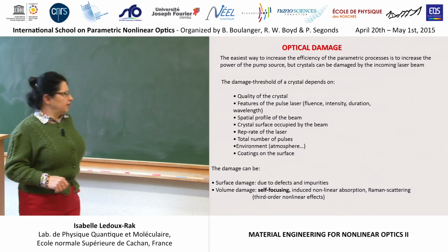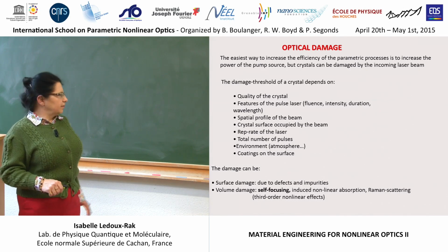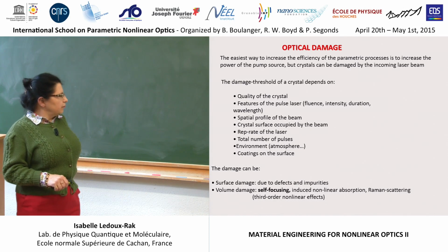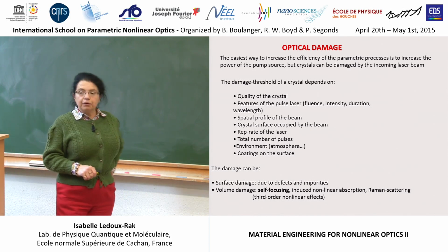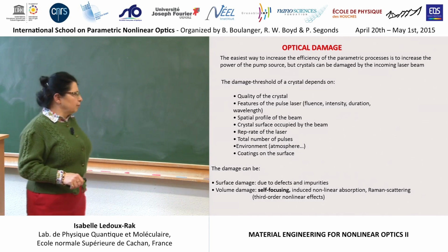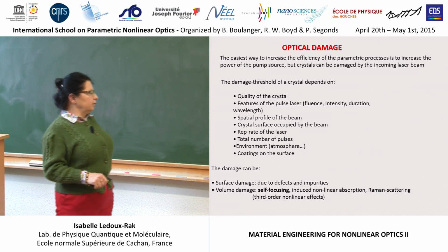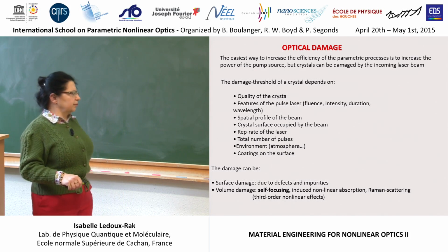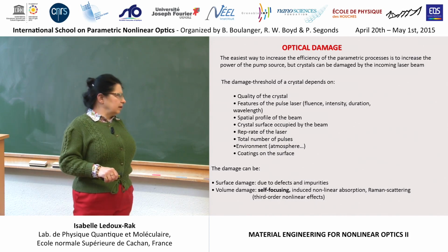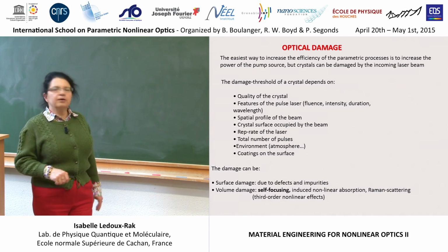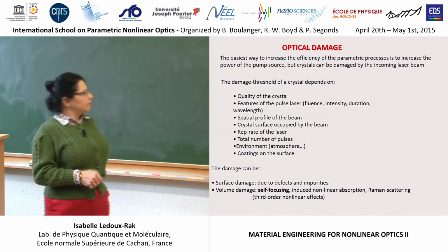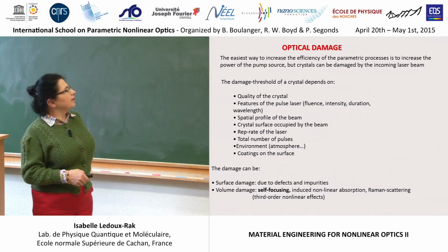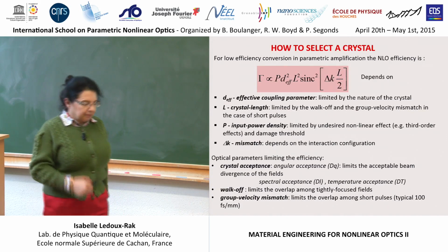And the damage can be on the surface due to defects or impurities. So it's not too difficult to solve if you protect the surface. The volume damage can also be induced by nonlinear effects, such as self-focusing, induced nonlinear absorption, or Raman scattering, all these effects being third-order nonlinear effects. So it's important to keep in mind that we must take care about these effects.